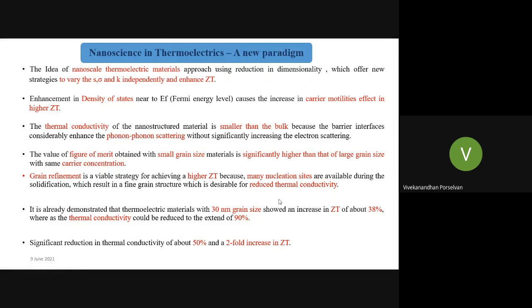The main idea of imposing the nanoscale in the bulk material is that as the size is reduced in a bulk material, what will happen? The surface area increases, the volume of the grain boundaries increases, and the triple junctions increase. So thereby it has become an active component to reduce the thermal conductivity. As we have a large number of grain boundaries, they will act as a barricade to reduce the transport of thermal energy from a higher energy state to a lower energy state. Thereby we can possibly reduce the thermal conductivity in the thermoelectric material.